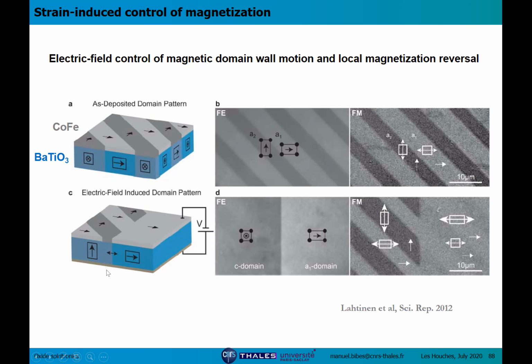domains in the pointing upwards. This does not affect very much the existing anisotropy from the previously deposited CoFe. But here, if you have a change in the A domain configuration, you induce a strong change in the anisotropy, and then the magnetic easy axis switches again.